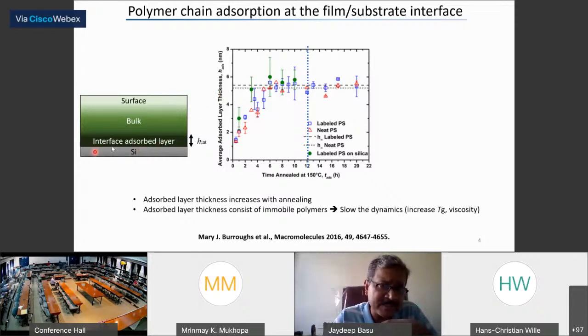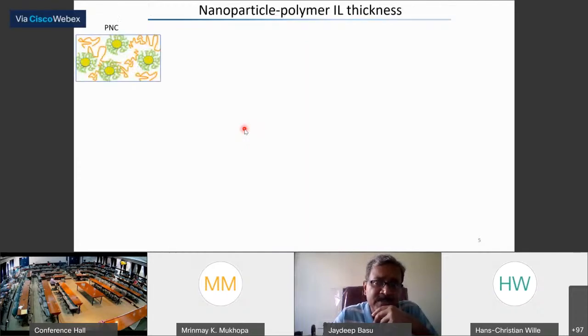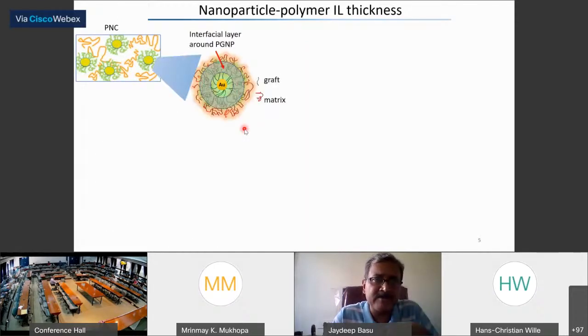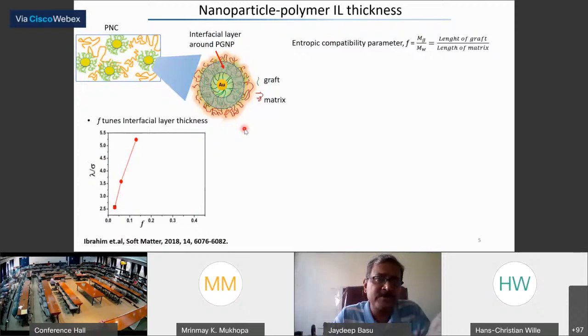So there is some sort of an interfacial layer in a polymer, but you can see similar behavior. For example, if you measure the glass transition temperature of the system, and one tries to correlate those behaviors with trends in such properties. So this is for pure polymer, but in the nanocomposite, or at least in the one that we are interested in, for that matter, for any nanoparticle polymer composite interface, there is another interface, which is now the interface between the particle and the polymer.